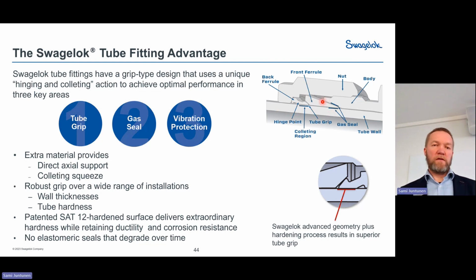Gas seal happens in the front ferrule, between the front ferrule and the fitting body, and the front ferrule and the tube, and we call it a burnishing and polishing action, which happens in there. So there are those peaks and valleys because of the machining of the ferrules or tube fitting, and all those will be polished away and create the sealing area. And the back ferrule also takes care of vibration resistance, so the robust grip on the tube helps with the vibrations.